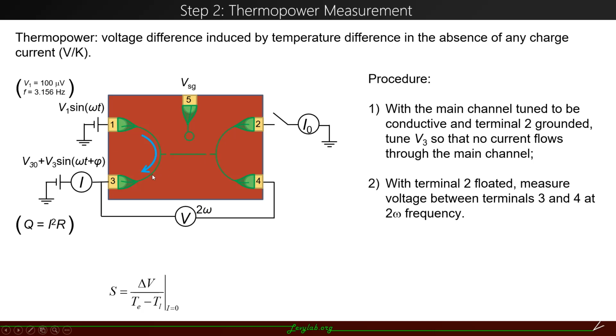Then in this way, we have generated a heat flux at a frequency of 2 omega because of the Joule heating. We can then use a lock-in amplifier to measure the voltage difference between terminals 3 and 4 at a frequency of 2 omega, which is exactly the thermal voltage generated by the temperature difference. With the thermal voltage measured, we still need to know the temperature difference to calculate the Seebeck coefficient.